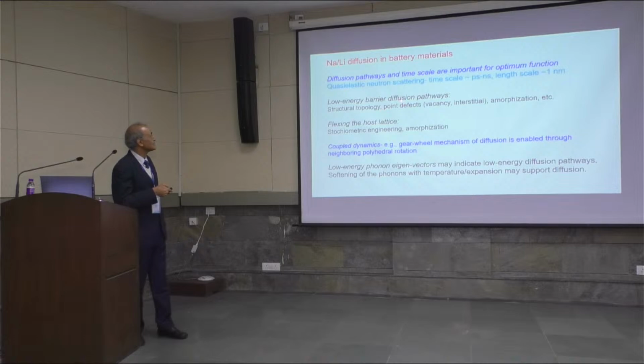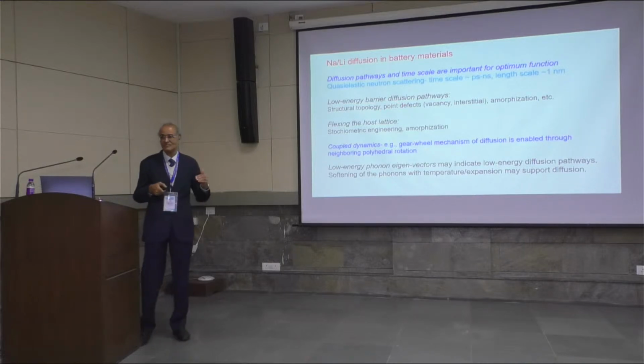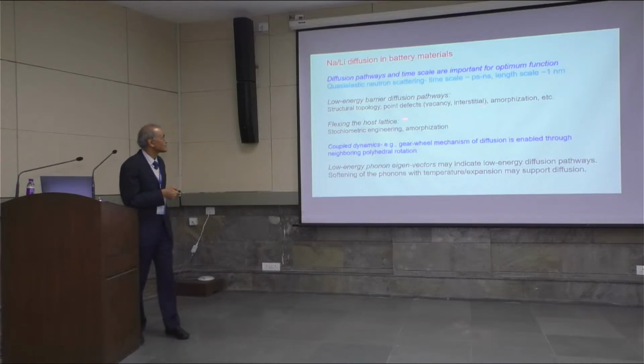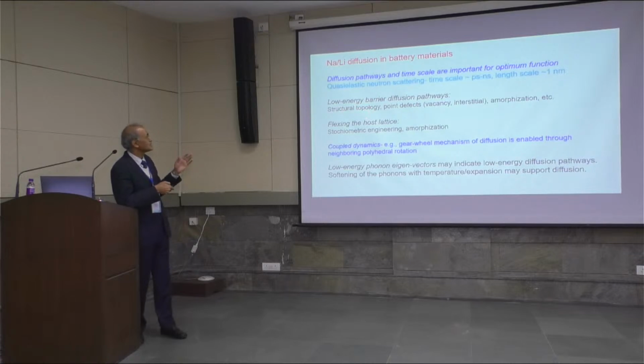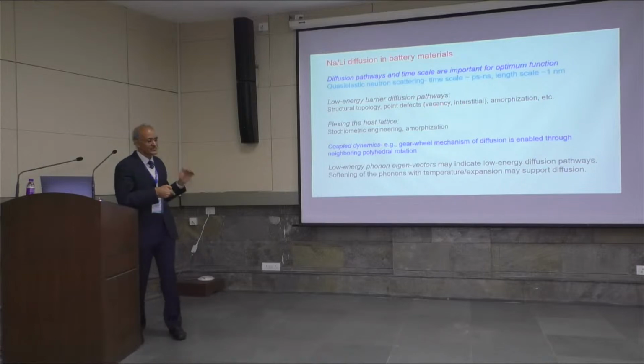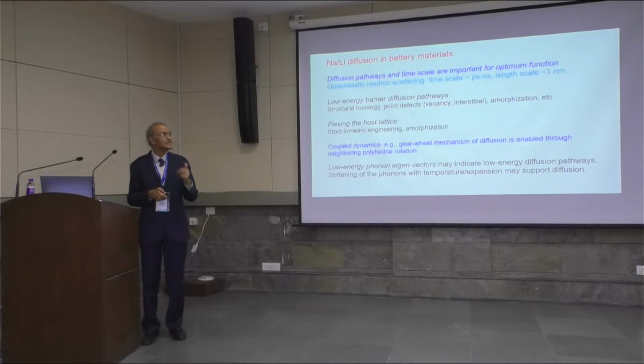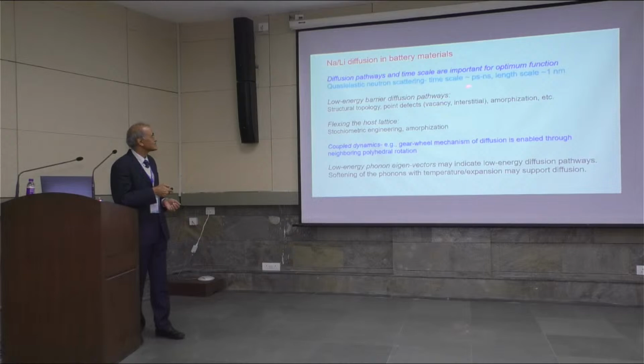And then you can very well imagine that you are looking for low energy barrier diffusion pathways. If the energy barrier for diffusion is small, then those will provide the preferred pathways. And that is what we would like to find out within materials. These can be helped in various ways. The structural topology, I'll take an example. And point defects are useful because the vacancies or interstitials help in the diffusion process. Another important thing is if you have an amorphous kind of structure, that has its own benefits.